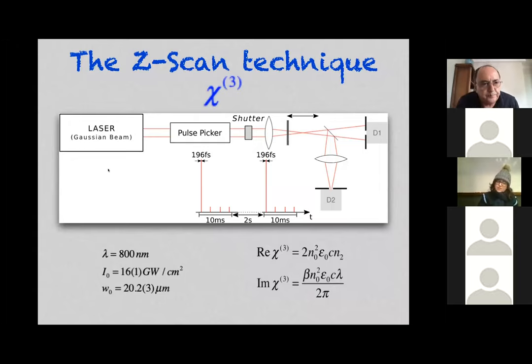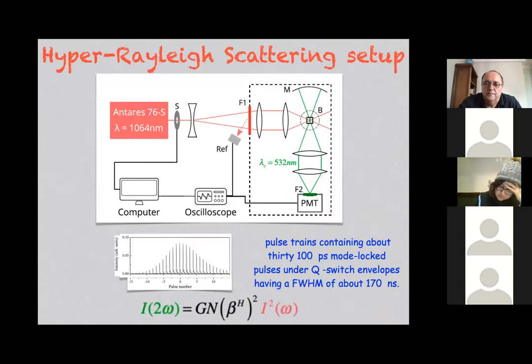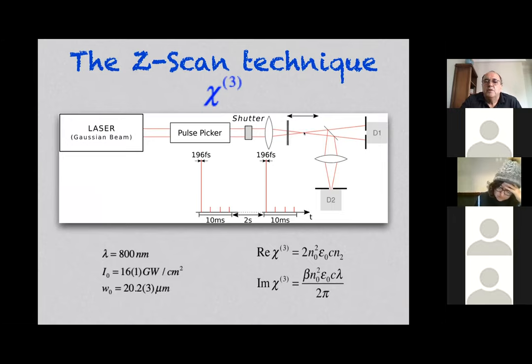In the case of electronic processes, as we are interested to discuss today, we need a laser which is pulsed, with pulses of about 100 or 200 femtoseconds. This laser is focused at that position. After that, there is an iris to measure in detector D1 the intensity of the fluence. But we can also do, at the same time, a different type of measurement, which is the total absorption. How do we do that? We put a beam splitter at that position. Part of the beam comes here and part of the beam is focalized in the second detector. So here we will measure the nonlinear index of refraction, and in this detector we will measure the nonlinear optical absorption.